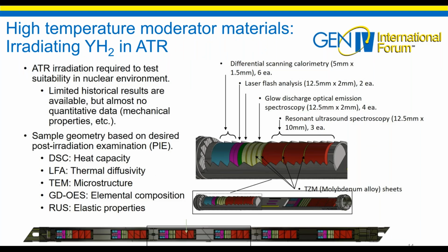Past characterization on yttrium hydride has occurred for fresh material, but now properties such as heat capacity, thermal diffusivity, microstructure, elemental composition, and elastic properties will be examined through post-irradiation examination. For this particular test, we will be putting in various samples of yttrium hydride fabricated using both techniques, the powder metallurgy and direct hydriding, at several different temperatures and irradiating it for several cycles if possible. We will be looking at those results and characterizing the measurements at the end.